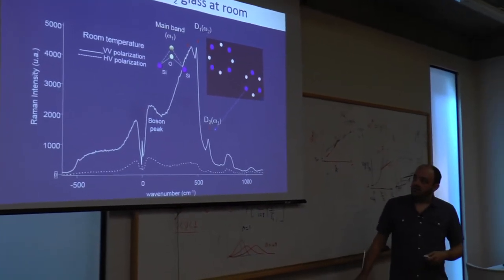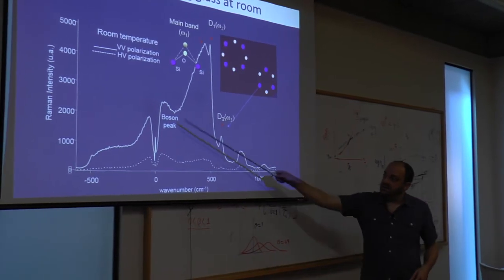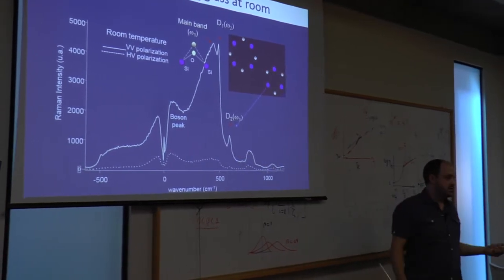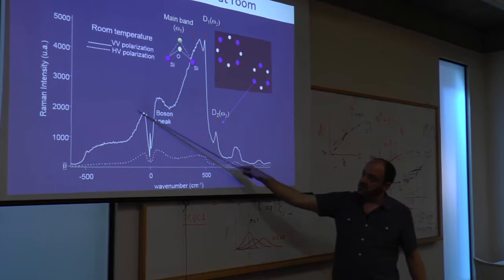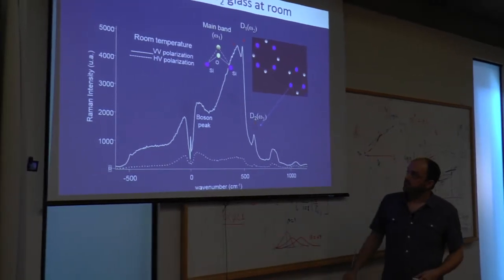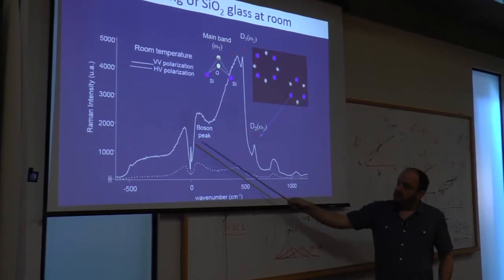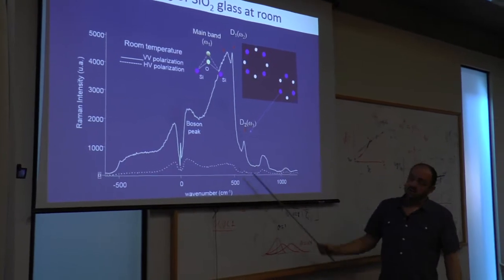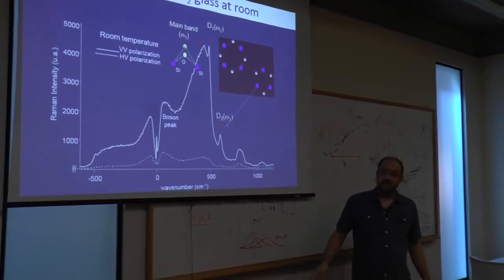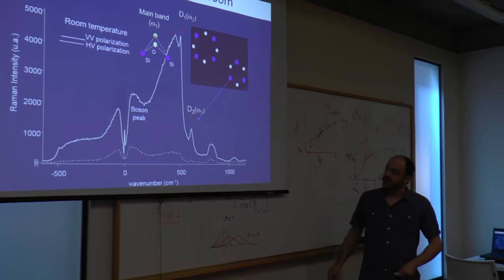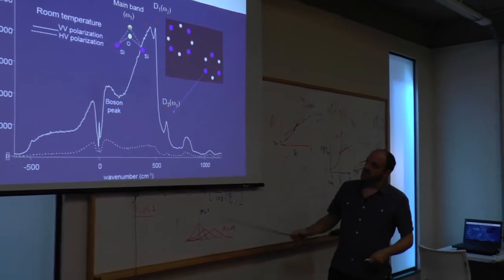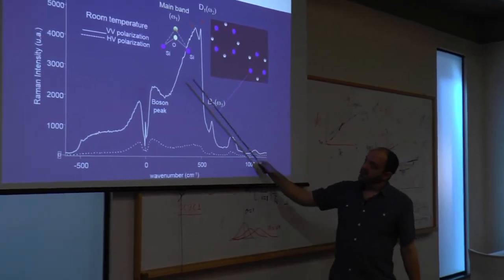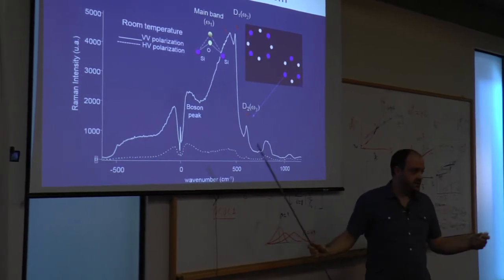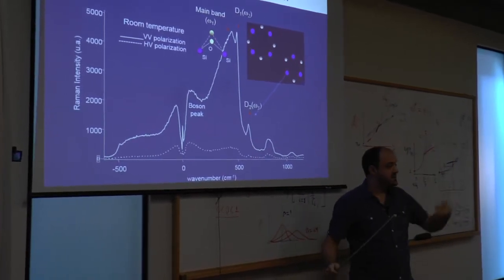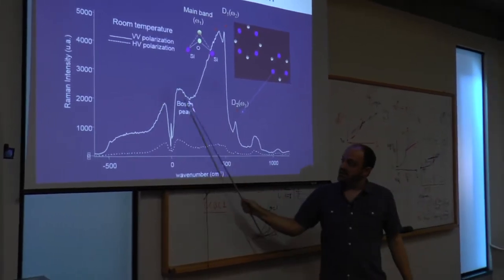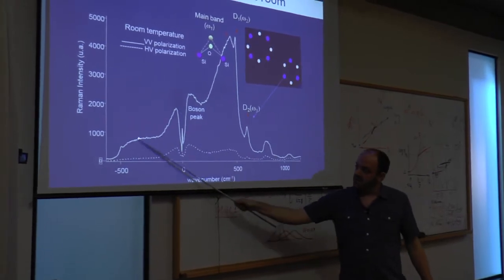One thing you can observe right off the bat is that the Stokes side is much stronger than the anti-Stokes in terms of intensity. Therefore, most of the time we use just the Stokes side of the spectrum because it's way more sensitive to the features that we're trying to look at. Don't worry too much about what these features are, but if we got equal amounts of photons that have higher frequency as lower frequency, the spectrum on both sides should be the same. And we see that's not the case.